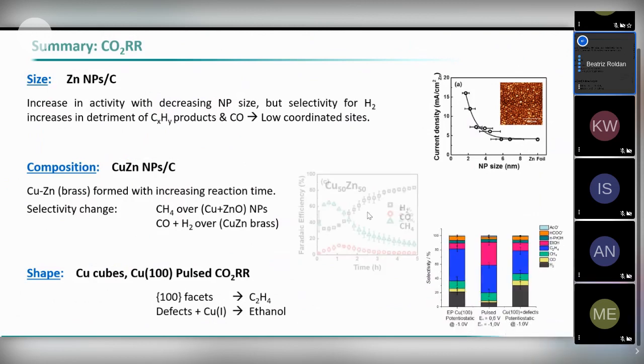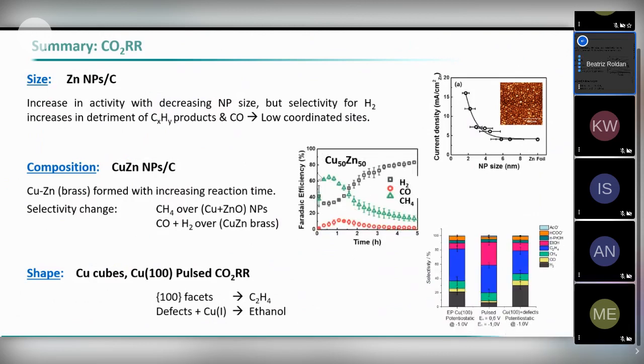I talk about the composition of the catalyst. And how is this important? Not just to look at the reactivity after 1 or 2 hours. In this case, our copper zinc catalyst was making methane for the first 2 hours or so. And then we see that the selectivity was changing, and we could explain why it was changing. The reason was that we start having the formation of brass, and on brass we make CO and hydrogen, not methane.